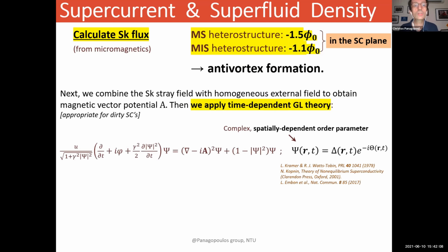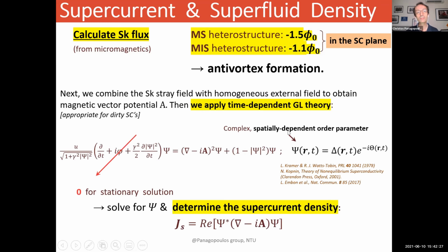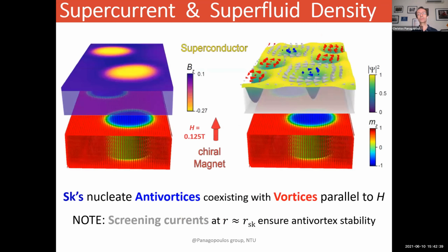The next thing we do is we combine the skyrmion stray field with a homogeneous external field in order to obtain the magnetic vector potential. Then we apply time-dependent Ginzburg-Landau theory, and from here we can calculate the spatially dependent order parameter for the superconductor. And we can solve for this order parameter and therefore determine the supercurrent density in our superconductor, JS. And this is the result shown in this schematic, which is the calculation.